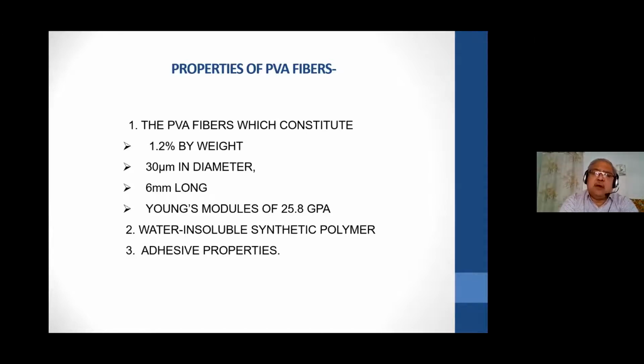This is basically called the aspect ratio of the fibers. We maintain that aspect ratio by considering the diameter to be 30 microns. We kept the 6 mm long pieces we chopped, and then maintained them thoroughly and uniformly mixed in the body of the concrete. The Young's modulus of that particular fiber, when we tested it, was 25.8 GPa. It is a water insoluble synthetic polymer and has some adhesive property. Basically, we could produce better results.